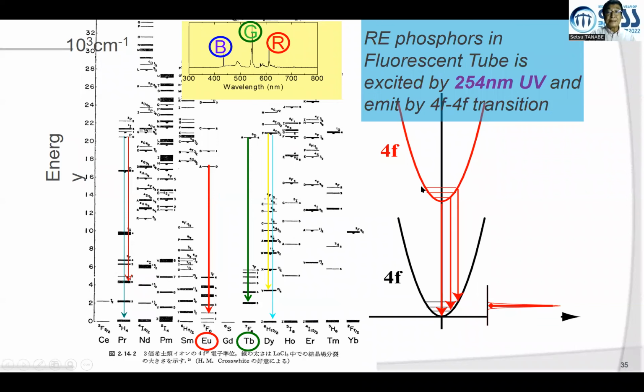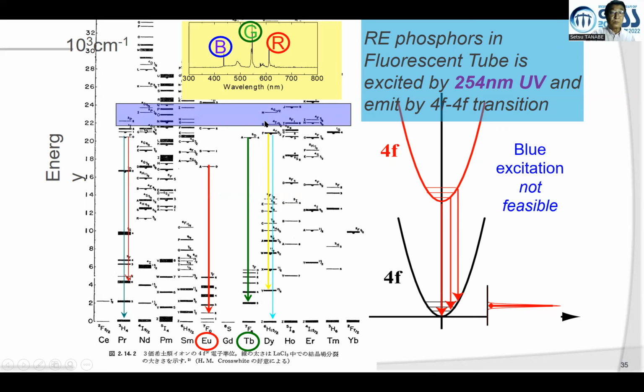Because of this, the offset of the excited state is not different from that of the ground state. The sidebands having different vibrational states have equal energy. As a result, the transition shape becomes very sharp for f-f transitions, as you can see. This is europium red, this is terbium green. There is no strong blue excitation band, and the f-f transitions are forbidden. There is no trivalent element which can be excited by f-f transitions. The exception is cerium. I will talk about it later, but not now.